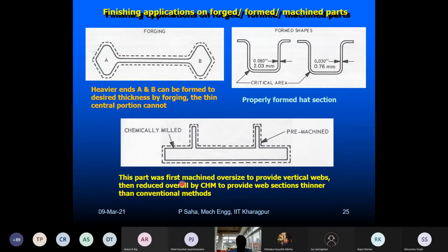And the third one is a kind of web structure. You see, this is one. This kind of web structure has thinner dimensions. These thin portions are first machined oversize. We leave the oversize and provide the vertical webs. But from the dotted line, if we try to machine further by conventional machining, what may happen? Because of the thinness, the moment you apply force during machining, it may deform, either temporarily or as a plastic deformation, meaning completely out of shape. So we do not take the risk. We machine up to this dotted line and leave it like this. For the remaining portions, we take the help of chemical machining. This is a standard practice.